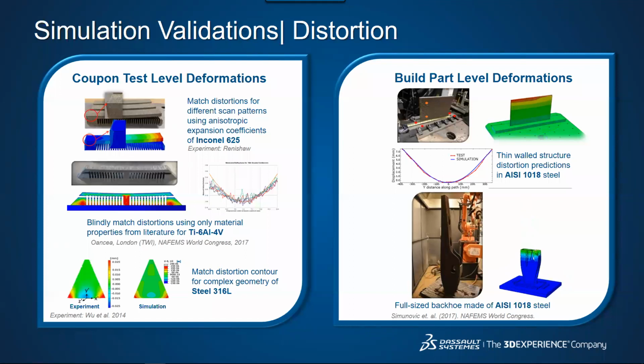and here we can show that we worked with Renishaw on using different scan patterns and matching distortions for these simple bridge geometries. We can also just use material properties from literature to blindly match various experimental results. This is because it's a full thermomechanical solution, so we don't need any calibration. We can use typical material properties to match experimental results.